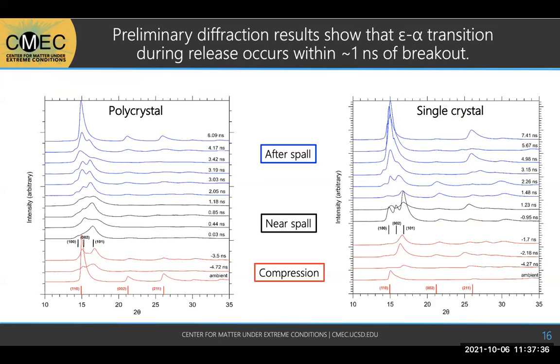Okay, so this is some of my newer results from the DCS experiments. The diffraction results show that the epsilon to alpha transition, that phase transition that occurs during the release, actually occurs within 1 nanosecond of shock breakout. And as a reminder, shock breakout is kind of like the start of spall.